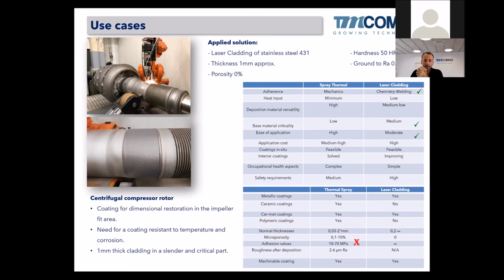And what is the better way of welding? Using laser cladding. Because this part is quite critical, as you know, all these parts turn at 5,000 or 7,000 RPM. So we cannot deform the shaft by laser, by welding, by PTA or by MIG welding. So we kept the choice of laser to not distort this rotor during the welding.